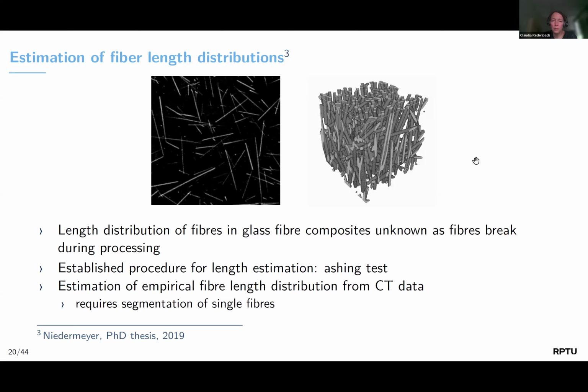So what we are investigating is how we could estimate fiber length distribution from CT data, which initially requires a segmentation of single fibers. That already is a challenge, but in addition, we see here that the estimation is hampered by edge effects. You see a lot of fibers are actually cut off by the image boundary. So we wouldn't know how long they actually are. We only know how much of them we see.